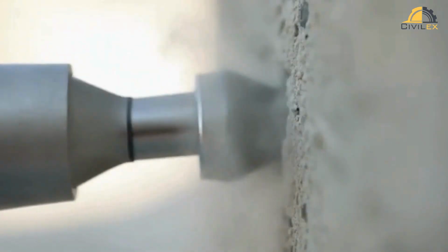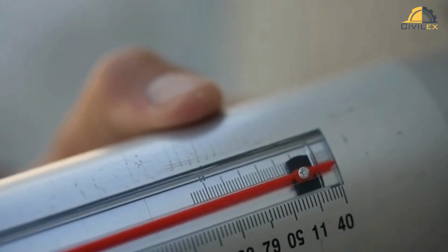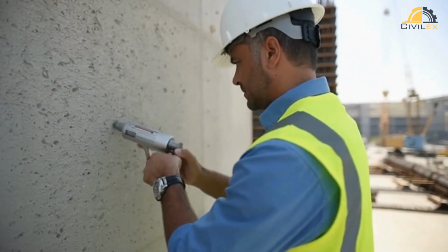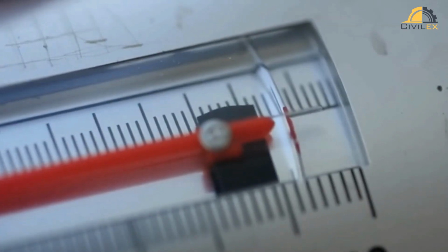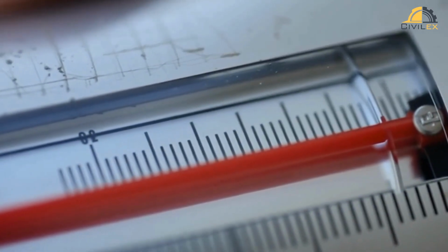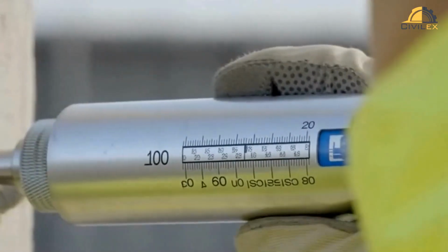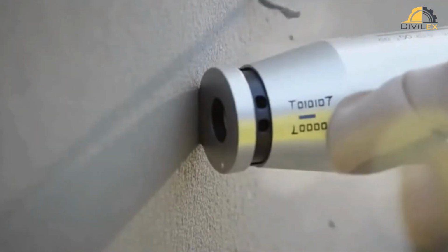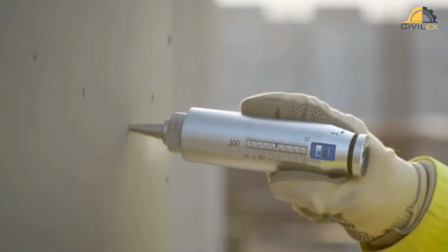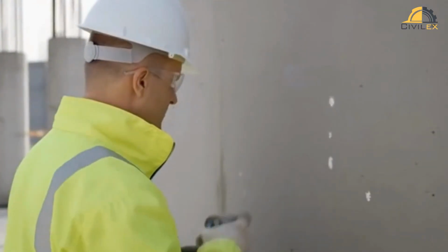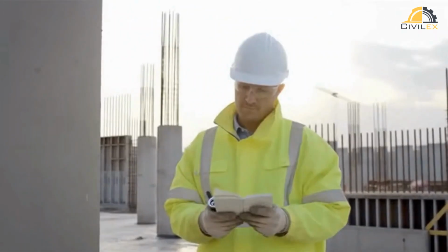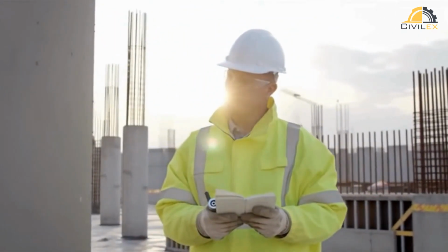But this test doesn't measure the entire strength. It's mostly about the outer few millimeters of concrete. So what can go wrong? A lot. If the surface is rough, wet, carbonated, or covered with plaster, you'll get misleading readings. That's why standards like ASTM C805 or EN 12504 recommend testing at least 10 spots per area, cleaning the surface, and averaging the middle values while ignoring the extreme ones.